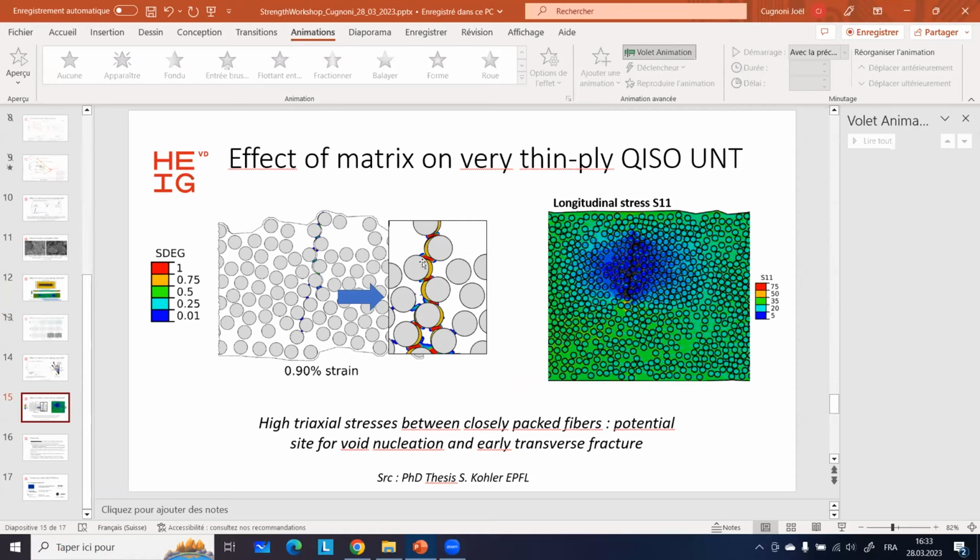And that's where the simulation gets into trouble, because these are really large strains that we have in these bundles. So we don't know exactly how the matrix behaves physically in this area. But for very small crack opening here, we cannot break the bundles actually due to the matrix ductility. At least that's what the simulation shows. So I think many of these effects of transverse cracking are related to the crack opening that we have here, and if we break the bundles or not, at least on the micro scale, it's one of the important aspects.